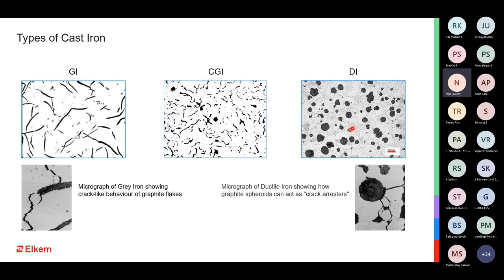On the other hand, you see this ductile iron microstructure where the graphite is in the form of spheres or mostly spheres, and the sphericity, the roundness of it, is nodularity, like we all know. So how is it different from gray iron? In this photograph, you can see that there are cracks, but these cracks get arrested because they do not have a smooth flow towards the other end of the graphite flake. In gray iron, the graphite flake acts as a crack initiator or crack propagator. In this case, the graphite does not act as a crack propagator, and it arrests the movement of the crack, thereby giving a much better mechanical strength, a much better tensile strength, to the casting.